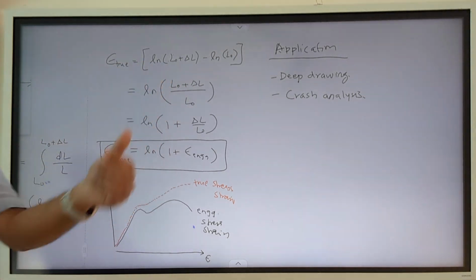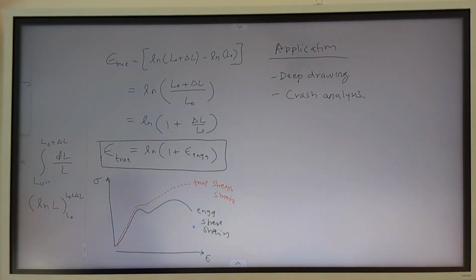In general, if you are using any finite element software, when it asks for stress strain data, it is always to be supplied in true stress strain rather than engineering stress strain. So when material property data comes to you, it will be in the engineering form, because the test report will be in terms of engineering stress and engineering strain. But if you are doing any finite element analysis, then you will have to use the true strain. That is in general any FEM software.